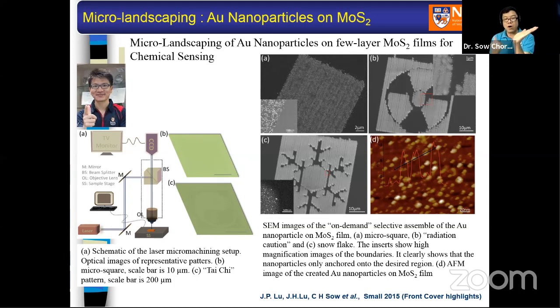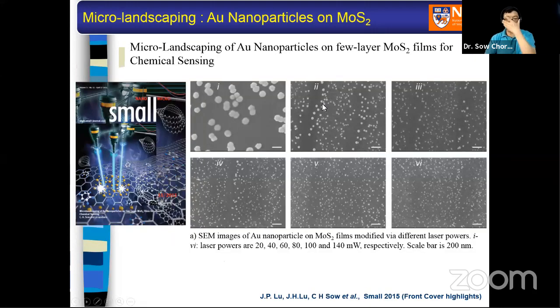You put a drop of chloroauric acid solution. Gold likes to look for sulfur. And so the gold would like to bond onto the sulfur very nicely. You just leave it for about 10 seconds, then you blow it away. And all the gold will find the sulfur region, that defective sulfur region that you created, which is the dangling bonds consisting of sulfur. The gold sticks onto that and forms this nice pattern. You see the SEM patterns of all these gold nanoparticles, which you can decorate on the surface. The cool thing is, I'm showing you 6 SEM pictures of the gold nanoparticles on the surface.